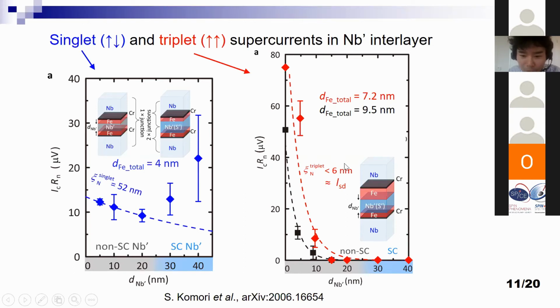But if we block the singlet component by preparing a thick iron layer, then we can see a totally different trend. In the normal state, we can see a very sharp suppression of this long-range triplet Josephson current. And we think it is related to spin scattering because triplet pairs are spin polarized and sensitive to spin scattering. And here, in this superconducting region, the interesting thing is we cannot observe any enhancement of supercurrent, which means long-range triplet pairs cannot mediate Josephson coupling with a singlet superconducting barrier inside.